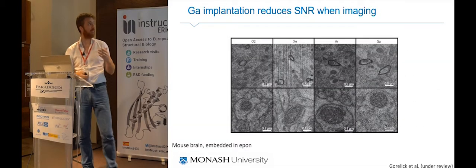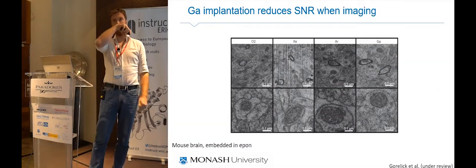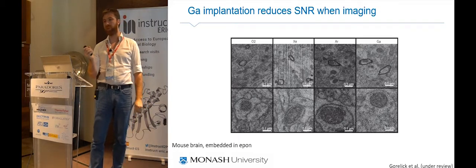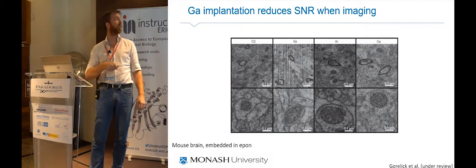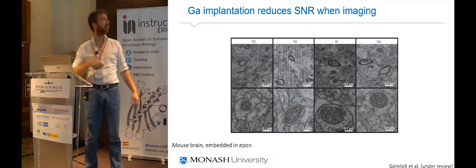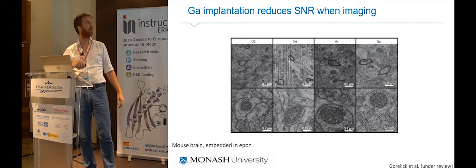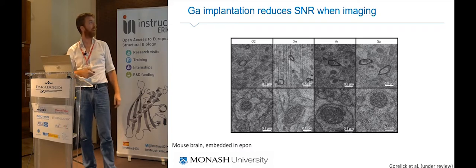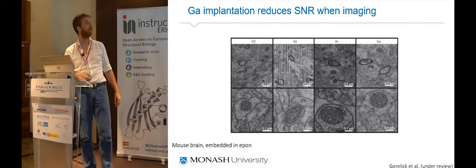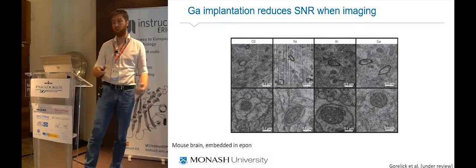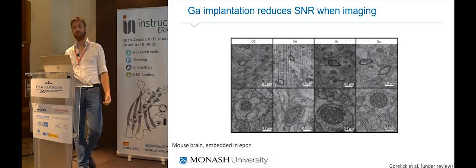But one thing that we did notice when doing some measurements, and this is an example, the same sample across, it's mouse brain embedded in resin, stained with osmium. So what we found is that there is very little contrast if you're using a liquid metal ion source compared to if you're not. So the contrast was improved if we were not using the liquid metal ion source to mill.